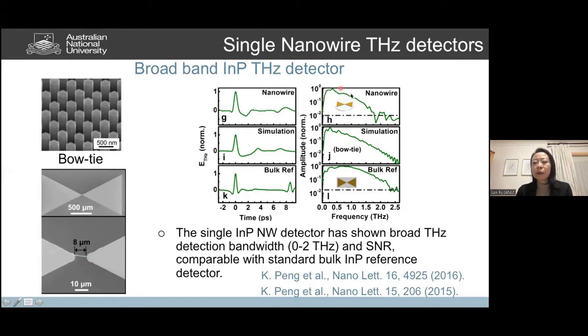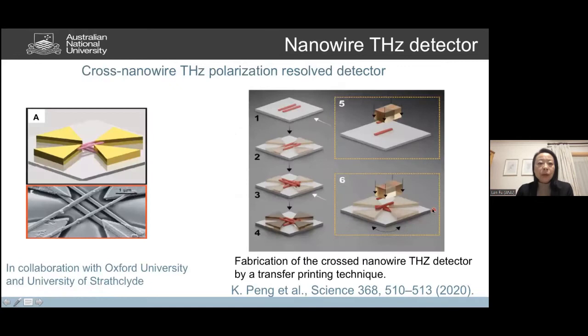So this is the signal measured from our single nanowire device. And we can see that this has a very nice signal to noise ratio compared to a bulk reference fabricated from indium phosphide substrate, which Michael Johnston's group use quite routinely for their terahertz spectroscopy system. The reason is that even though we have a very tiny material, we are able to reduce the dark current by using a very small volume of material, thereby we can get a good signal to noise ratio.